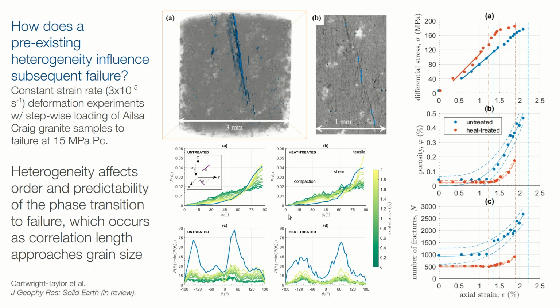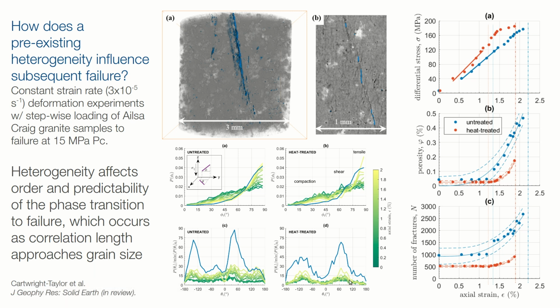And in this case this is an analysis of the orientation of those fractures, where we see that certain early imprinted orientations actually get inherited and control the ultimate failure geometry. So Alexis showed here essentially that heterogeneity affects the order and predictability of the phase transition to failure, and that is related to the correlation length when that approaches the grain size.